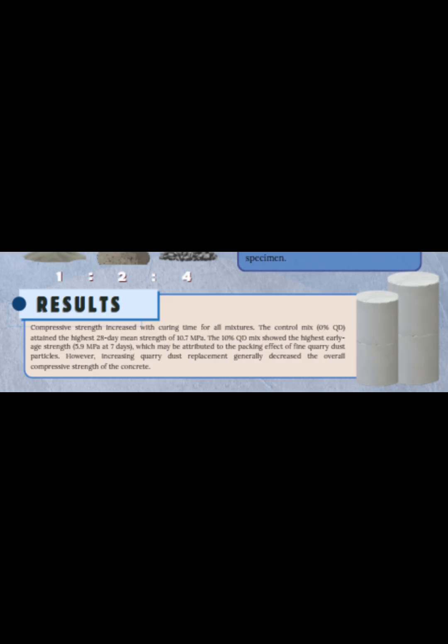In conclusion, quarry dust can be incorporated into concrete as a partial replacement for cement. However, based on our findings, higher replacement levels resulted in lower compressive strength compared to conventional concrete. While quarry dust shows potential as a sustainable construction material, further studies are recommended to determine the optimum replacement percentage that balances both strength and environmental benefits.